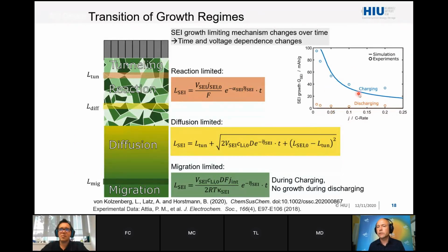The physical reason for the enhanced increase of SEI growth during charging is that if you charge, the electrons are basically transported toward the electrolyte, and if you discharge, the electrons are transported to the outer circle. This bias causes you to create more interstitials during charge than during discharge, and this makes this asymmetry. Again, here we have this very huge dependence on the potential and the overpotential, and what I'm going to show now is that this huge dependence on the overpotential is responsible for an inhomogeneous SEI growth across